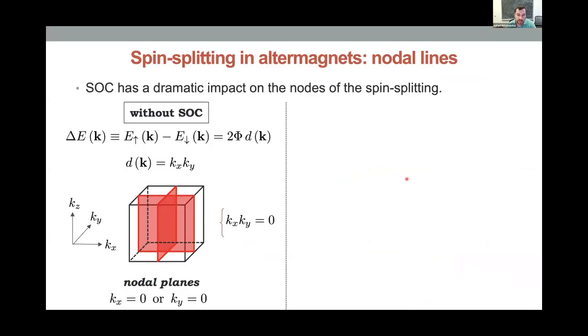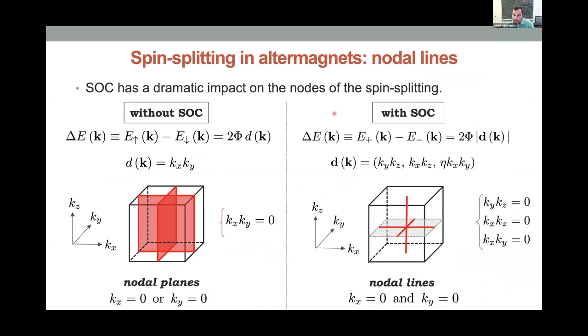Now let me talk a little bit more about how the effect of the spin-orbit coupling will impact the nodes of the spin splitting. So without spin-orbit coupling, spin up and spin down, you get a splitting proportional to the d-wave form factor, which vanishes along two planes. So you have nodal planes, and that's a generic property of altermagnets, the existence of nodal planes of spin splitting. Now, when you turn on spin-orbit coupling, as I mentioned, now you have this d vector, and every element of the vector needs to vanish. And this actually happens along three lines. So you reduce the nodal planes to nodal lines. Okay?